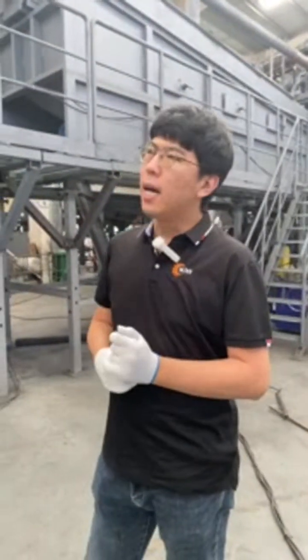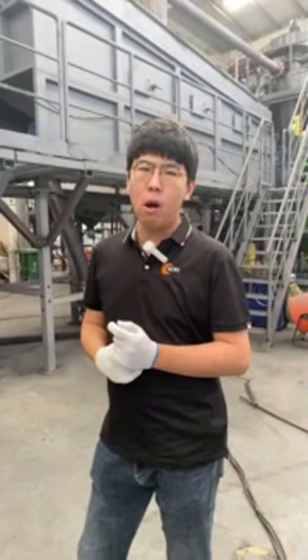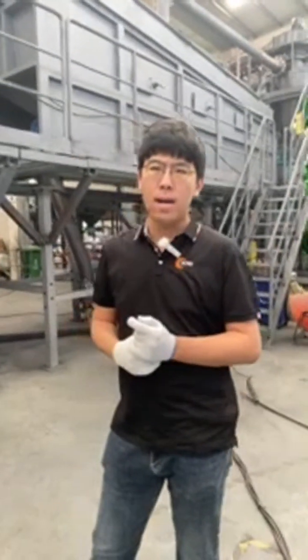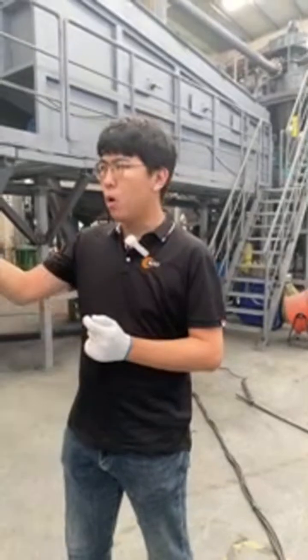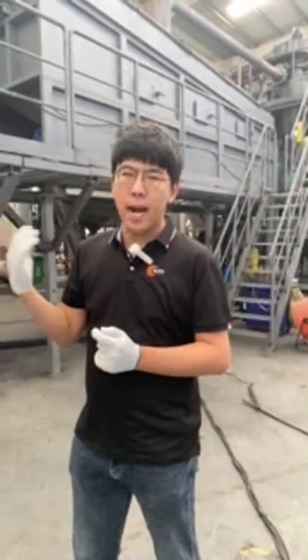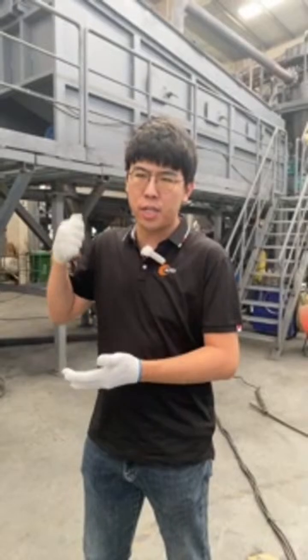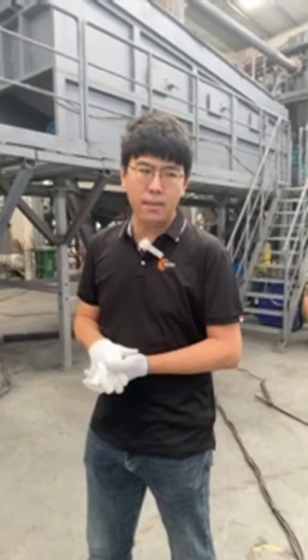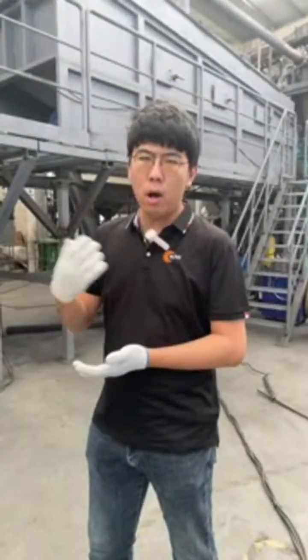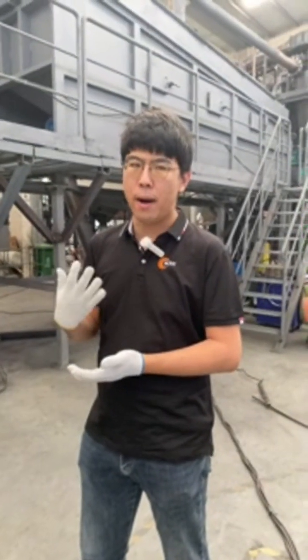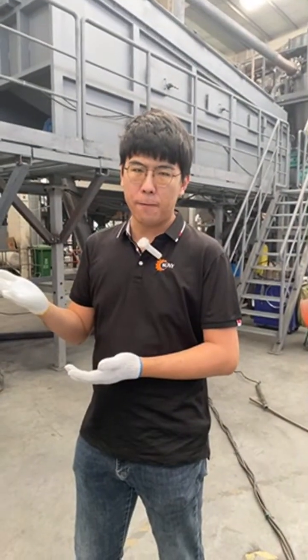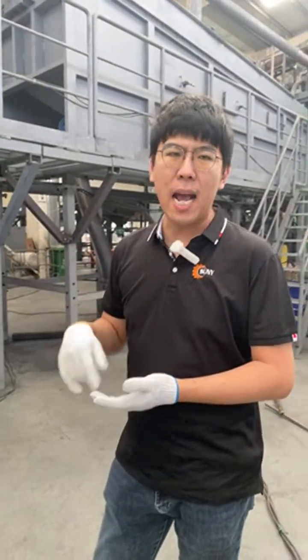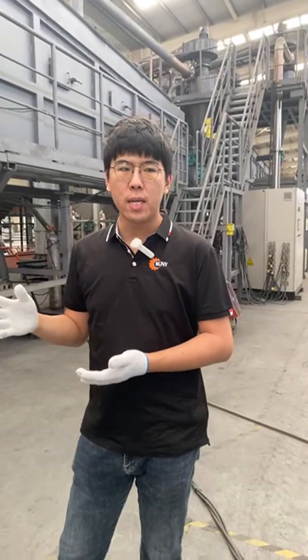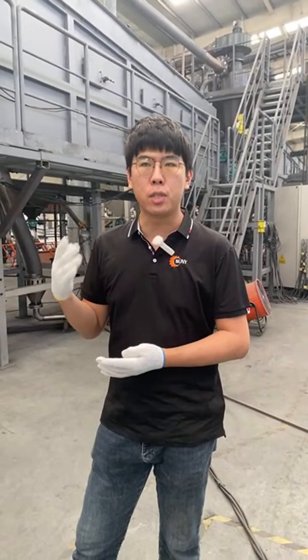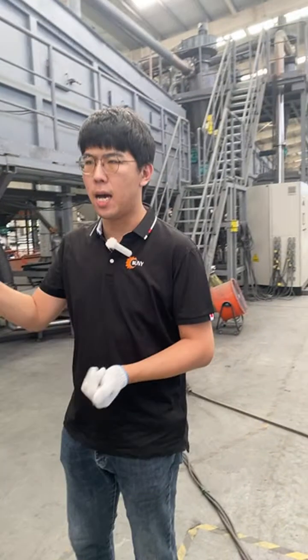And secondly, the purity. Inside the black mass, we will call aluminum and copper the impurity. So if you don't heat up, there is adhesive inside. You need to crush it very hard to remove the black mass. But during the crushing, you will also take out some aluminum and copper. So this part is impurity. But after heat up, black mass will be much easier to remove. So the black mass purity will also be higher. I hope this solves your question.